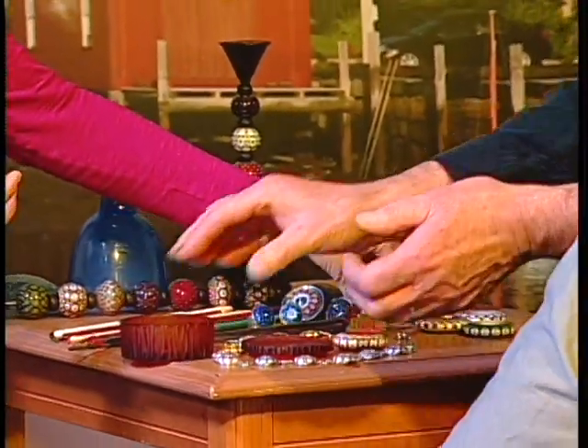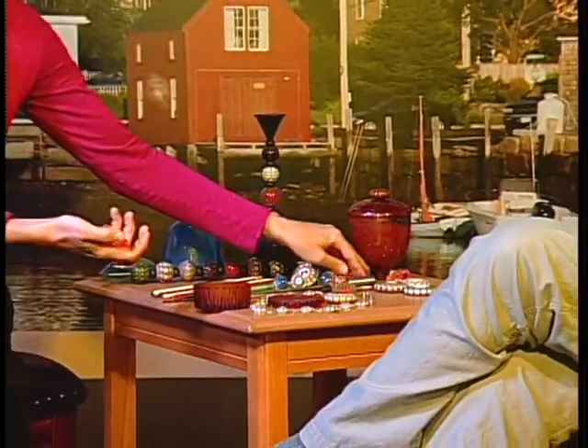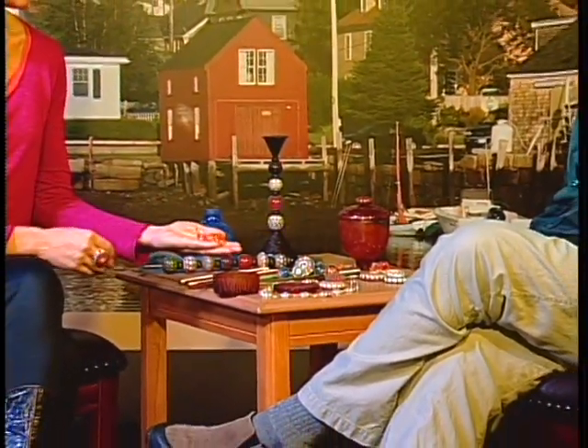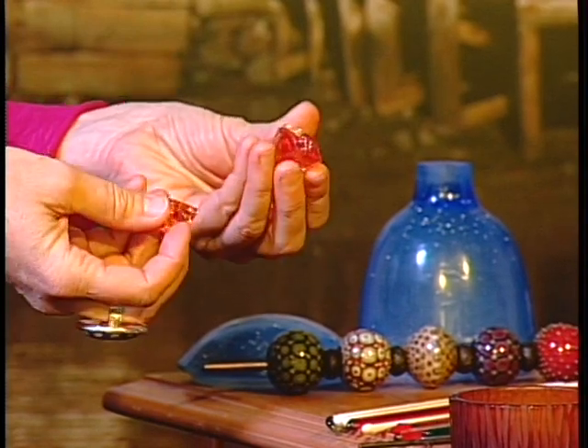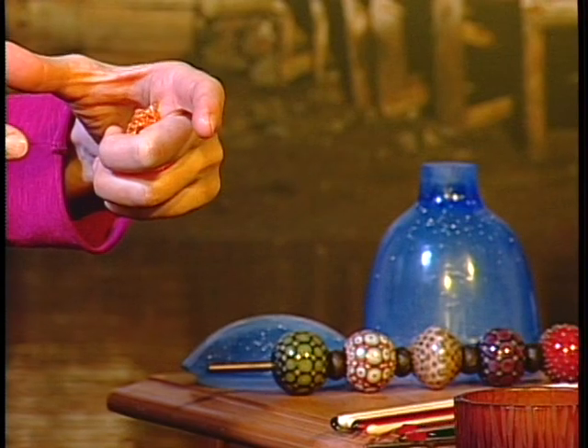So in that negative space, that plaster that has the wax that's been melted out, I put this crushed glass. And this can be crushed even finer. Like I can put really fine silt, almost glass, in there to create different color changes. Or I could use bigger chunks. So this glass then gets put on the top, and then I put that whole unit into a kiln.